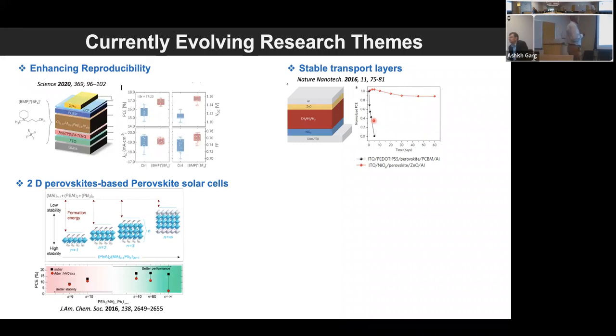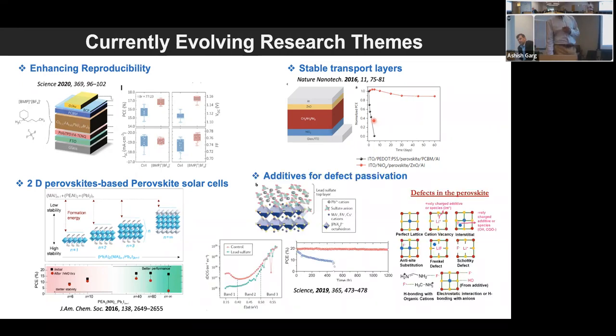Another is the use of 2D based perovskite solar cells. Methyl ammonium lead iodide is a 3D perovskite. It has high efficiency but lower stability. So 2D perovskites, which are more horizontal structures, have higher stability as compared to 3D perovskites. But the problem with 2Ds is that they have very poor efficiency. They tend to be more resistive, and in terms of charge transport, they are worse as compared to 3D. So the concept is to mix 2D and 3D and make layers which can be reasonably conducting. With a slight compromise of efficiency, you can achieve higher lifetimes. So some groups are working on this kind of approach.